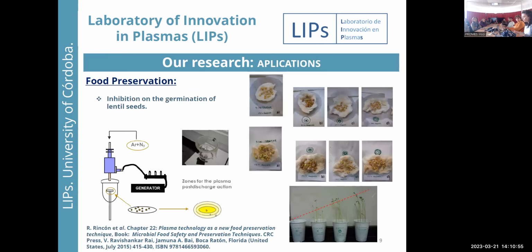Then food preservation. As I said before, we work very closely with Professor Michel Moisan from the University of Montreal. He developed a way of doing the sterilization of microorganisms and so on, so we thought that we could extrapolate that information and apply it to food. At the beginning, we worked to reduce the germination rate of lentil seeds. We applied a post-discharge of our argon nitrogen plasma, and what we observed is that those lentils that had been more directly in contact with the plasma greatly reduced their germination rate and also their growth, as you can see in this slide.